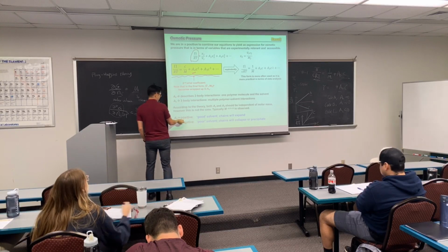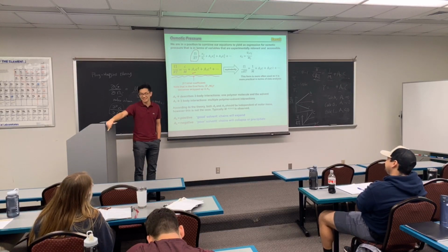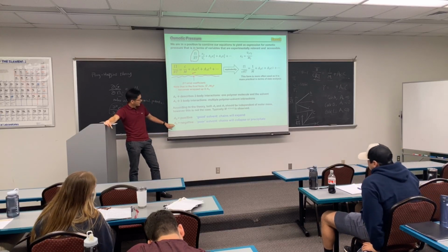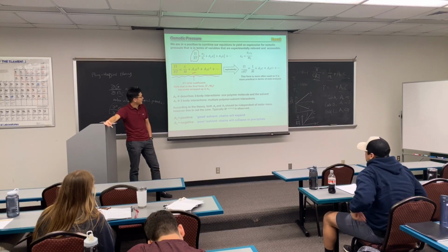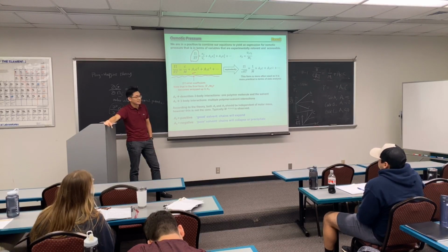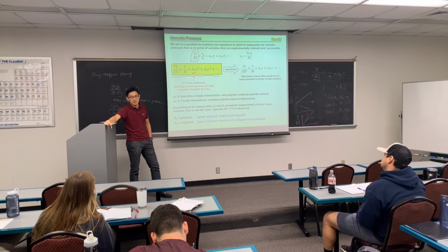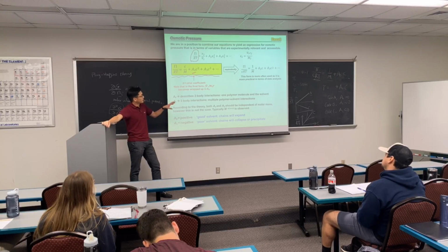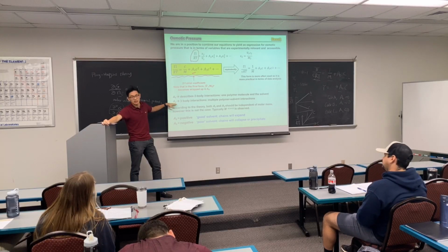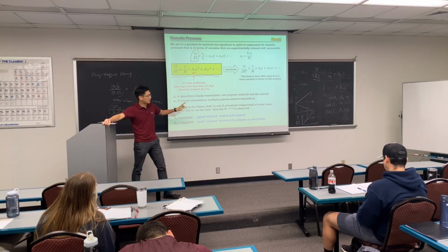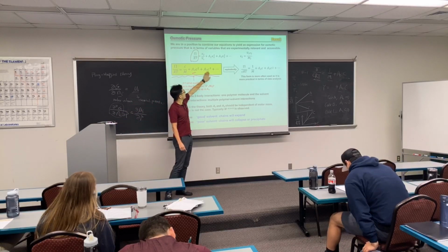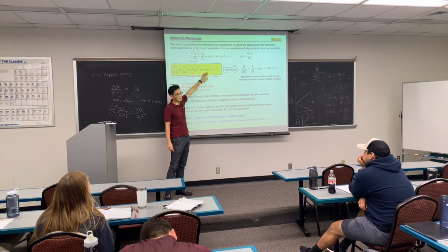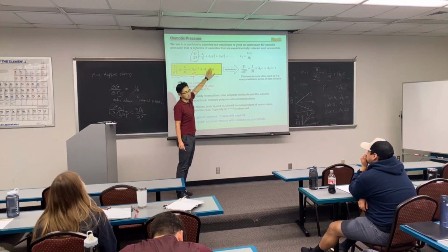All right, we kind of already showed here. If A2 is positive, the chains will expand. If A2 is negative, that means it's a poor solvent. Okay? And the third coefficient is basically strictly coming from the interaction between polymer chains, which is very small in most cases. It won't influence the results, so we only need to consider two terms. As you can see, C has a power dependence of 3, and in a very dilute solution, this term is minimal.